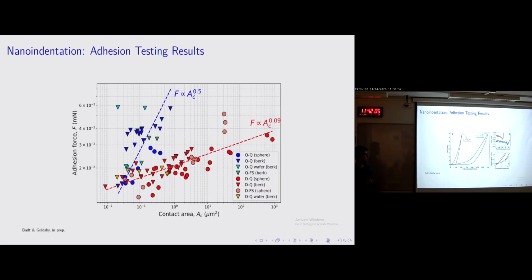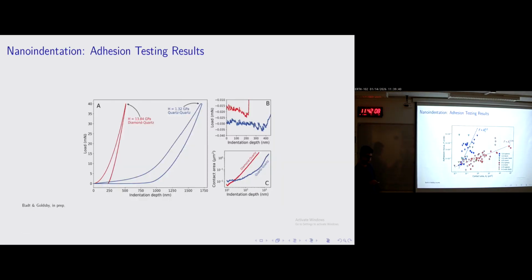And what I found is this. Wait. Yes. Can you go back? Yes, of course. What does this hysteresis plot show actually? You go to zero depth at around 1,000 nanometers when you're unloading, okay? And what happens then? You do a negative load to pull it? What is this flat line? It's not really flat. It's just the scale, we're talking about 0.02. It just changes angles. It's because we're starting to pull it apart.